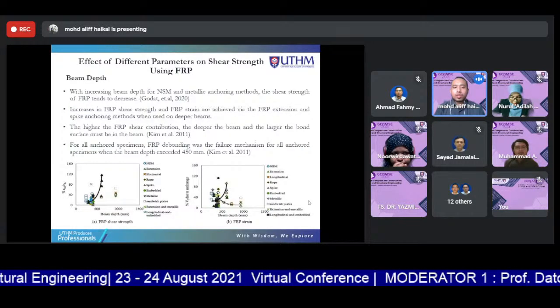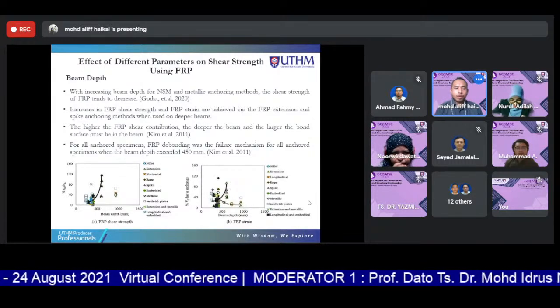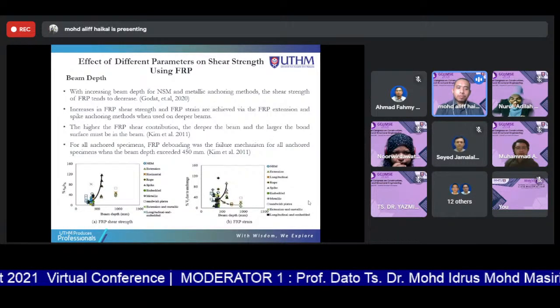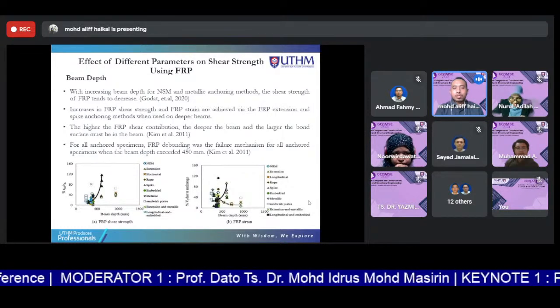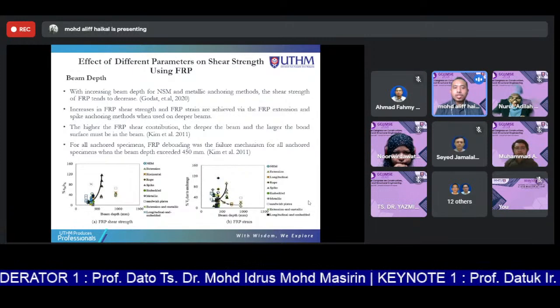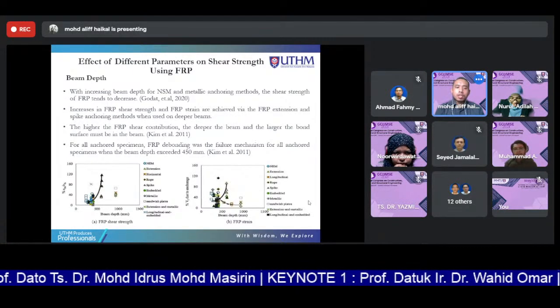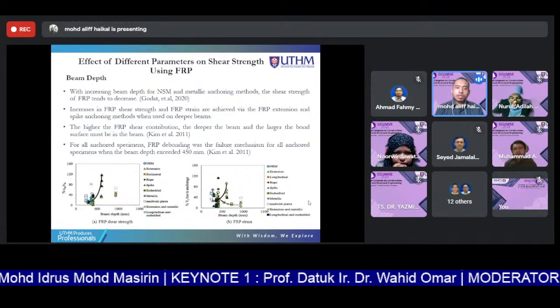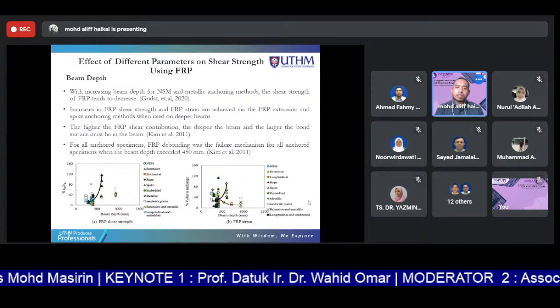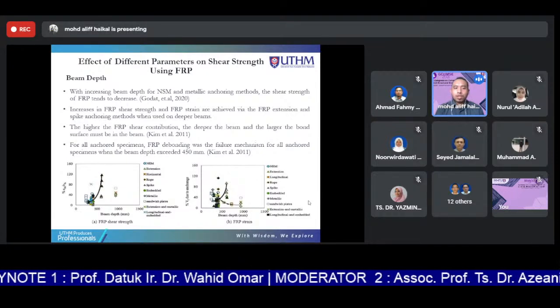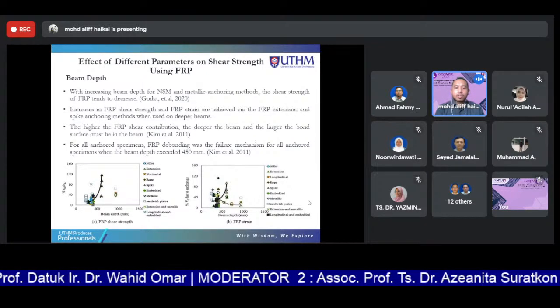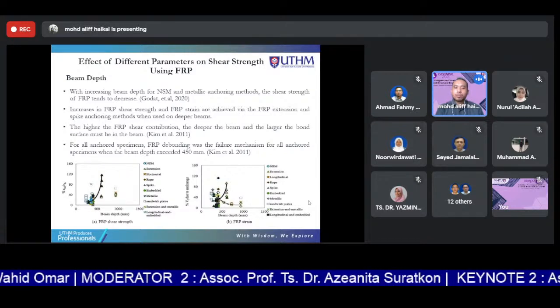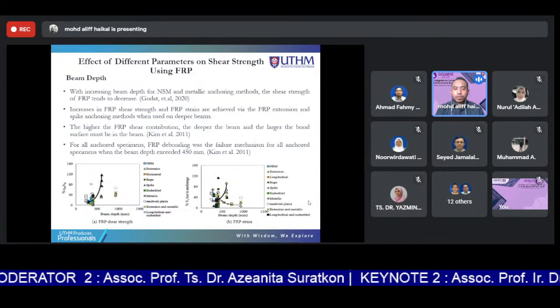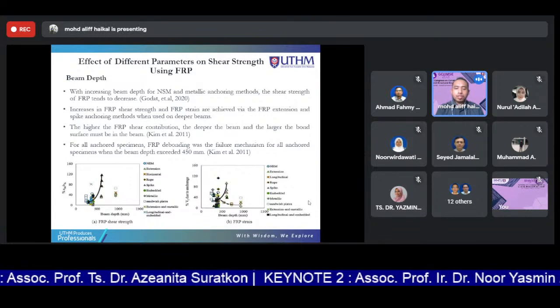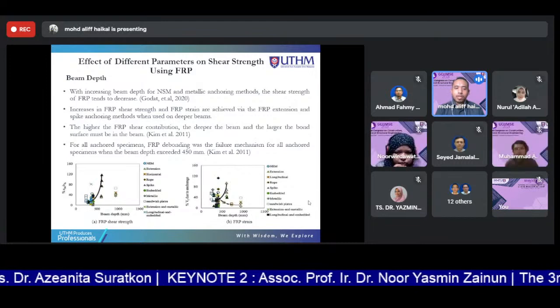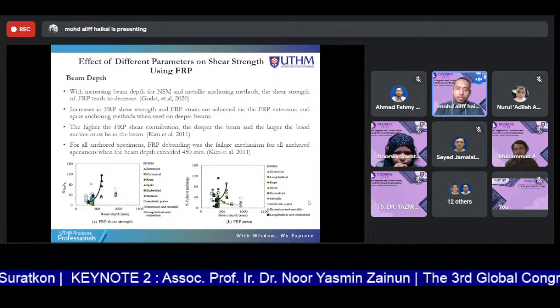And next we go to the effect of different parameters on shear strength using FRP. For the beam depth, as we increase the depth for the NSM and metallic anchorage method, the shear strength of FRP tends to decrease. An increase in FRP shear strength is achieved via the FRP extension and spike anchorage method when used on deeper beams. The higher the FRP shear contribution in a deeper beam, the larger the bond surface must be. For all anchorage specimens, FRP debonding was the failure mechanism when the beam depth exceeds 450 mm.